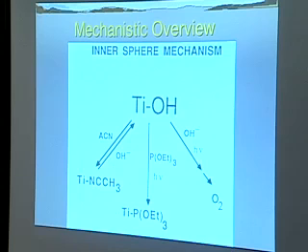And in the case of the acetonitrile, this is what you see. If you go to pH 7, remember where we're just seeing no kinetic isotope effect and where we're oxidizing water, it doesn't matter how much acetonitrile you add, you don't affect the lifetime of these transients at all. Okay, so water appears to go by an outer sphere type of mechanism, its oxidation.